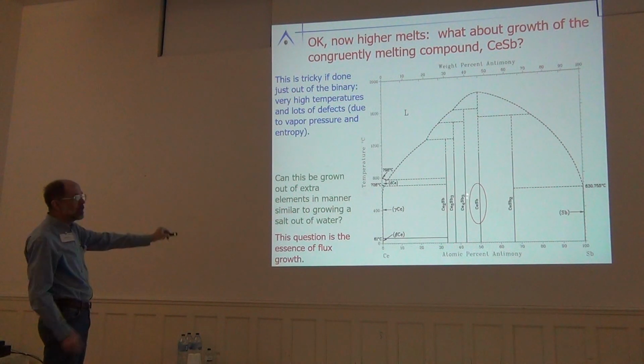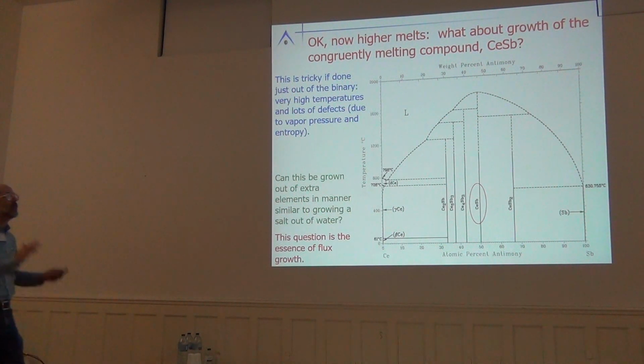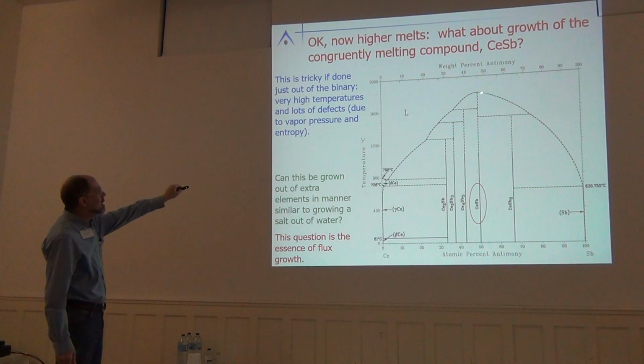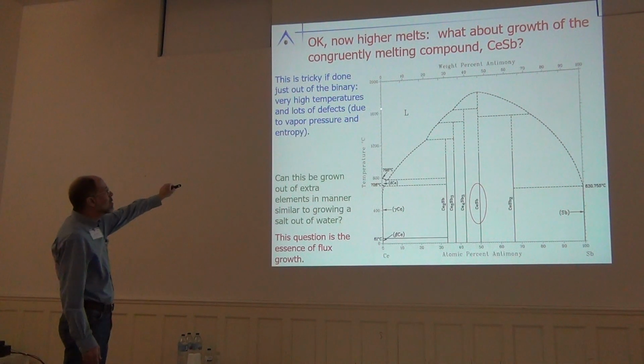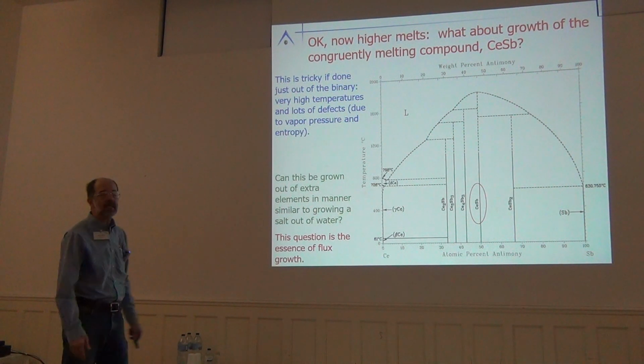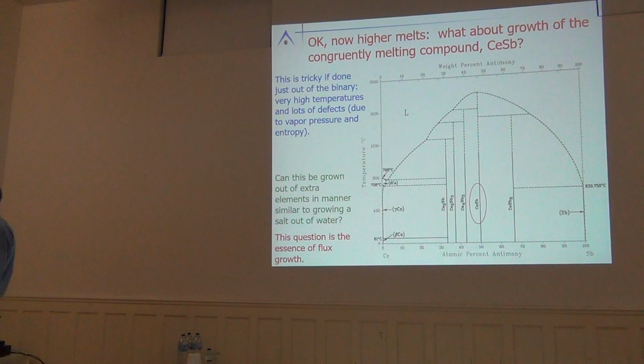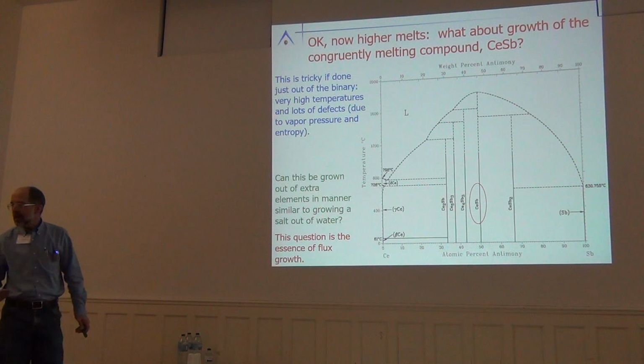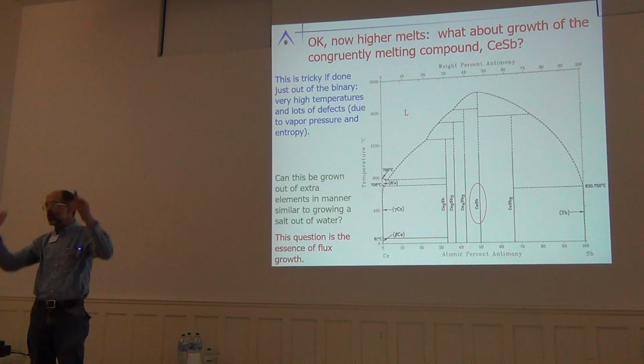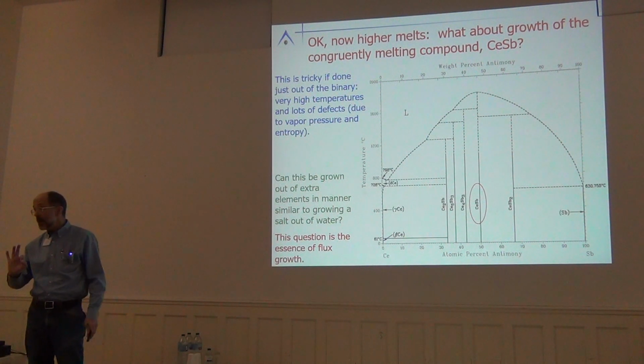Okay, this is congruently melting, so you can say, yeah, I just have a homogeneous liquid, I cool it down, I'm done. Except, this homogeneous liquid requires you to get around something like 1700, 1800, which is a really, really, really high temperature. The vapor pressure of antimony will be obscene, cerium will be rather nasty, the reactivity is hard, and let us not forget entropy. Okay, because the entropic disorder at that temperature is not small either.